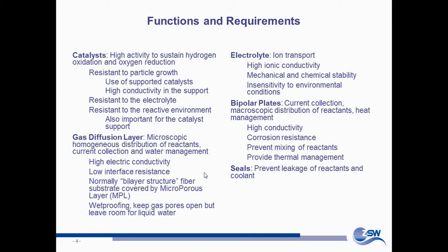And that's one of the reasons why many materials which are pretty good hydrogen oxidation catalysts or oxygen reduction catalysts are out of scope for PEM fuel cells, since PEM fuel cells are typically based on an acid electrolyte. And so there is little which is resistant to acid electrolytes at the potentials you find in a fuel cell. It also has to be resistant to the reactive environment.